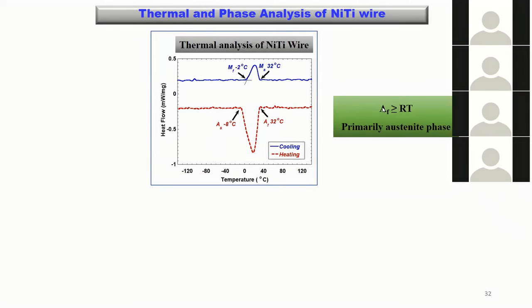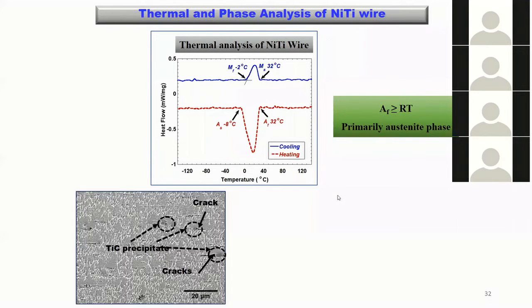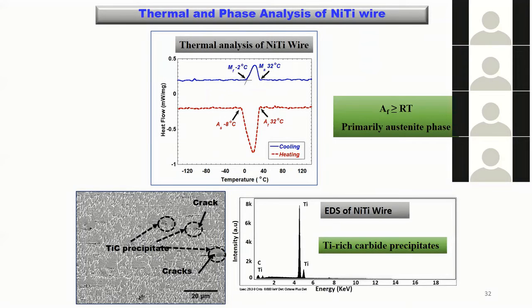Okay, so at room temperature, which for our country is most of the time around 30 degrees centigrade or so, we have dominantly austenite phase at room temperature. Okay, and again, doing the phase analysis through X-ray diffraction, we can see that there are some precipitates.